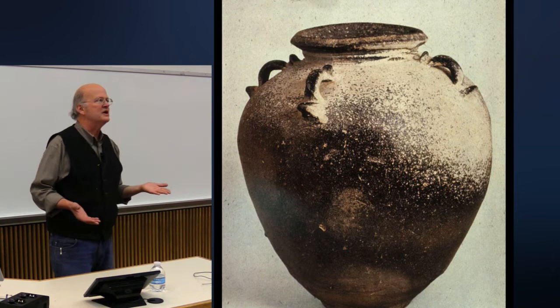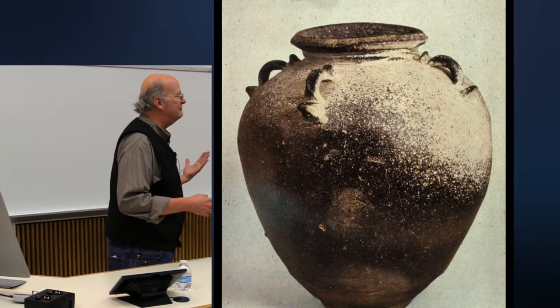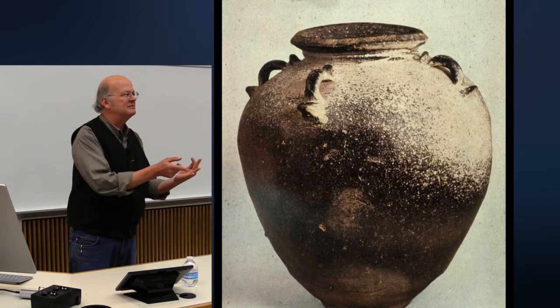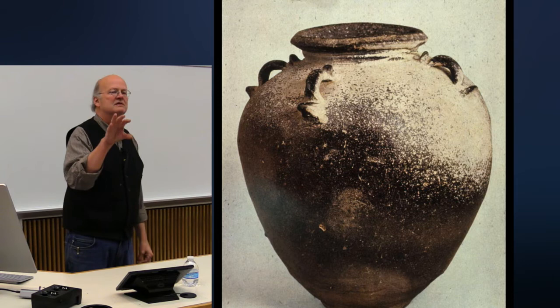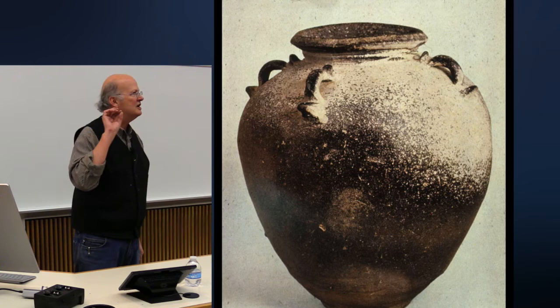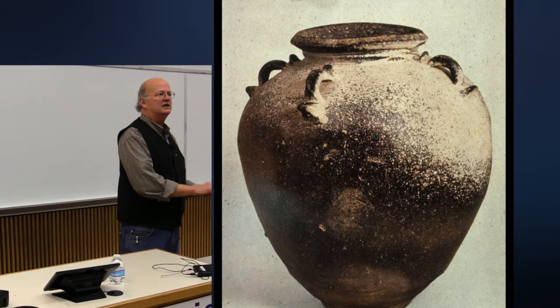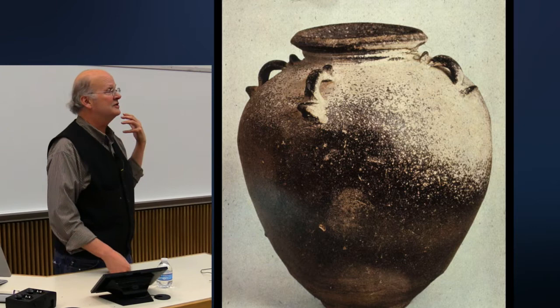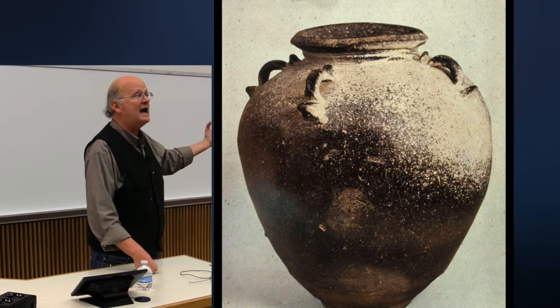It happens to be made up primarily of calcium, magnesium, sodium, and potassium. Actually, it's the oxides of those things. That combination by itself doesn't readily melt. It takes the addition of silica and alumina. Remember I mentioned earlier that kaolin is primarily silica and alumina. And as soon as that wood ash can react with the alumina and silica, then all of a sudden it makes glass. That's what we've got going on here.